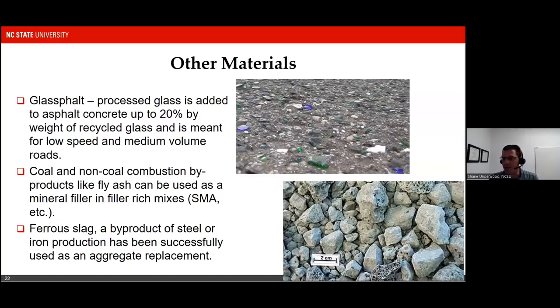It's not widespread, mainly because the economics don't often work out. In order to make glassphalt economically viable, you have to have usually a municipal glass processing plant and a municipal asphalt plant, because there, as a city, you're diverting the waste stream directly to another source of material that you as the city are buying. But not many states find this as an economically advantageous use of glass. One of the minor issues that we worry about on glassphalt is skid resistance, because the glass particles themselves have a very low microtexture. That's usually controlled by keeping the volume at a fairly low value. You'll also see glassphalt used in non-roadway applications like sidewalks, parking lots, some residential streets, etc.